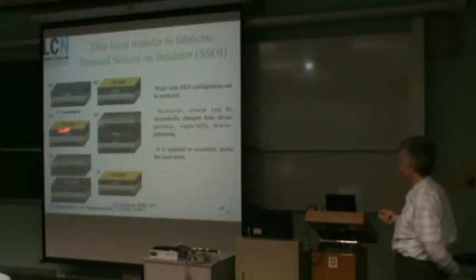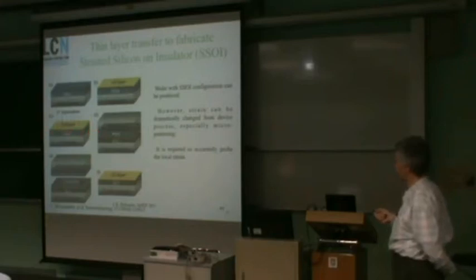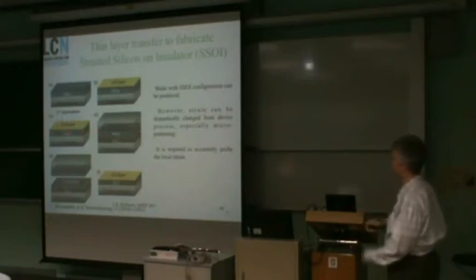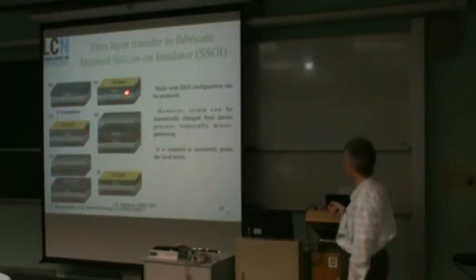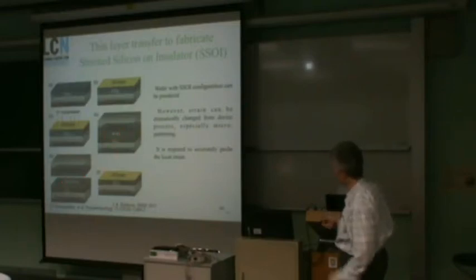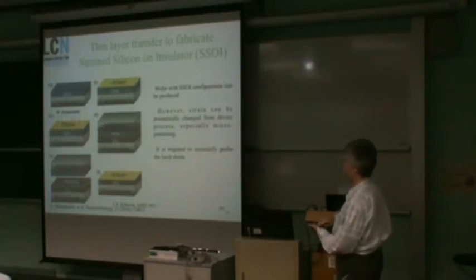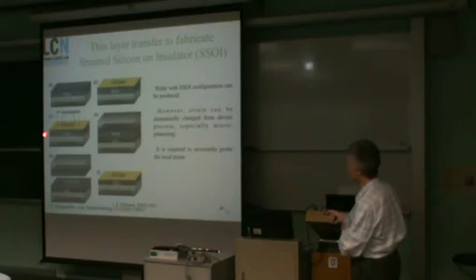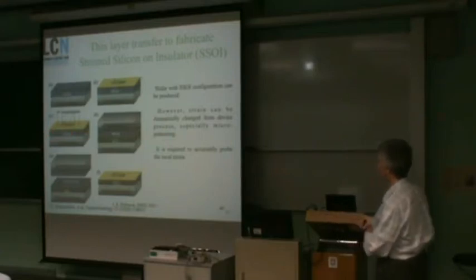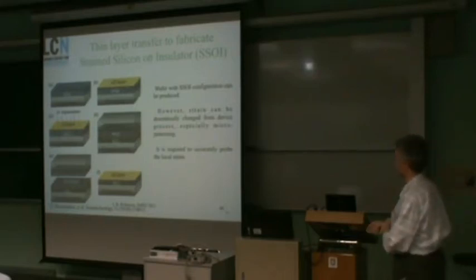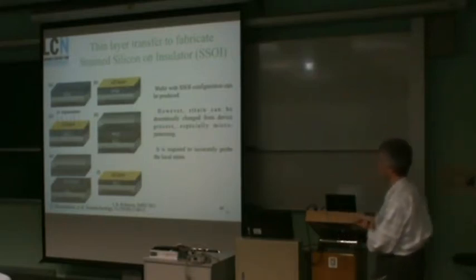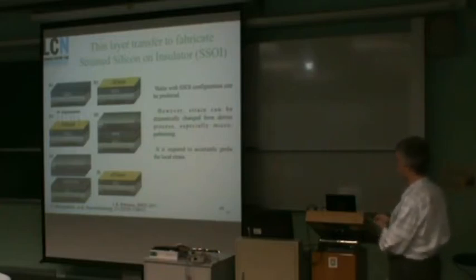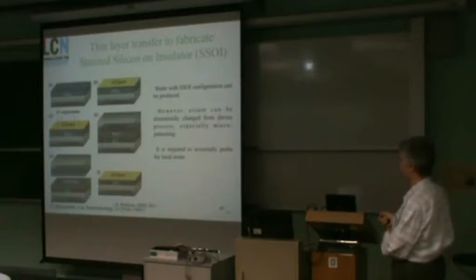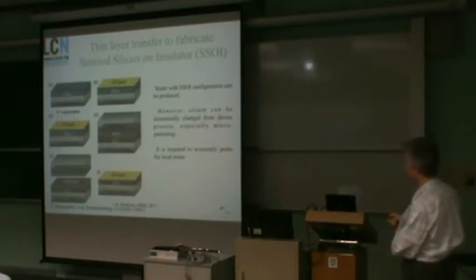And then you implant it with hydrogen ions to generate a fracture plane, so that when you then bond it to a handle, you can then break it and transfer the strained silicon onto it. Sorry, you turn it over here, as shown by the upside down writing, and then you can exfoliate and remove the damaged layer, which is this red implanted line inside this. Soitec calls it smart cut, and there's probably other trade names for this method of wafer bonding. And this is one of the standard ways of making SOI, but it also works for strained silicon on insulator.